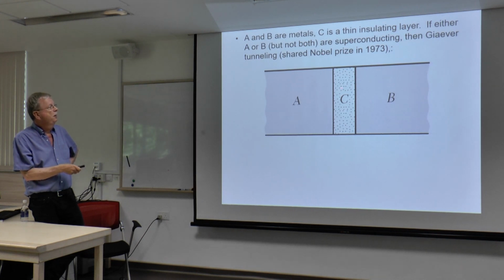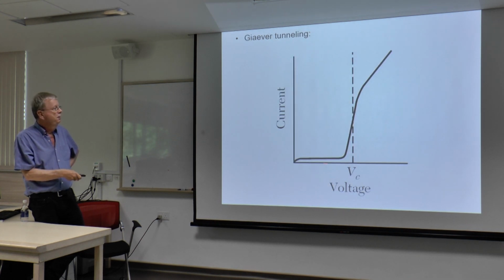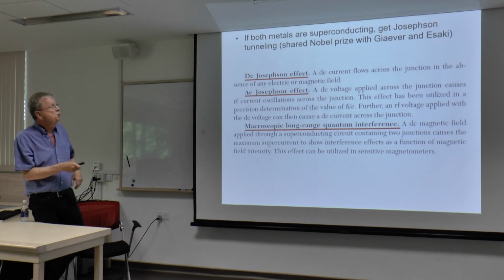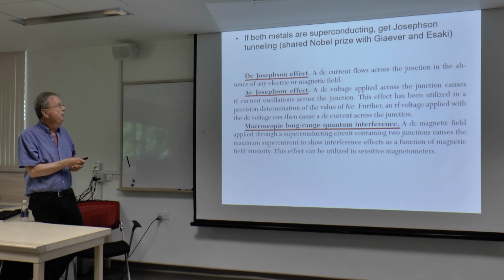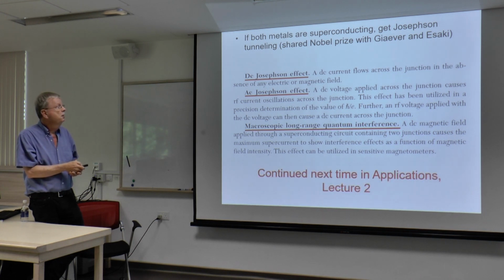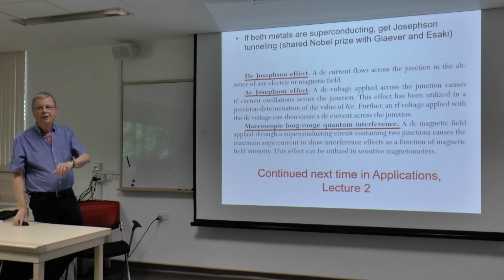So if I take an insulating layer, one is superconducting, one is not, and Giaever showed that there was something called Giaever tunneling, which is not much conductance through the barrier, and then you exceeded the gap on the superconductor side, and then you get conductivity that looks like this as a function of voltage. And so sharing the Nobel Prize with Giaever were Brian Josephson and Leo Esaki, and these are the three flavors of Josephson effect, or two flavors, and then quantum interference, which is, of course, very important in devices these days, and continue next time.